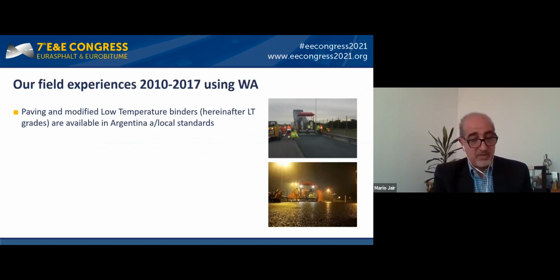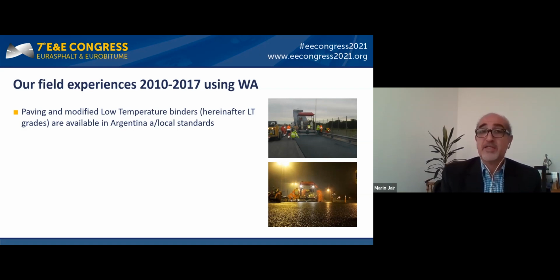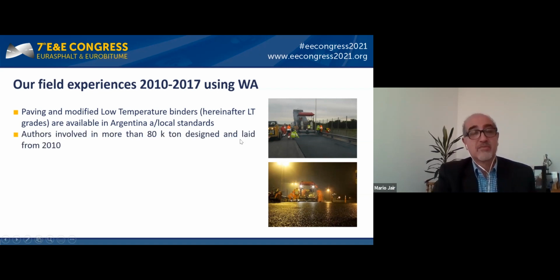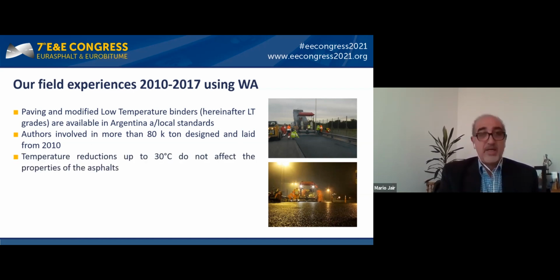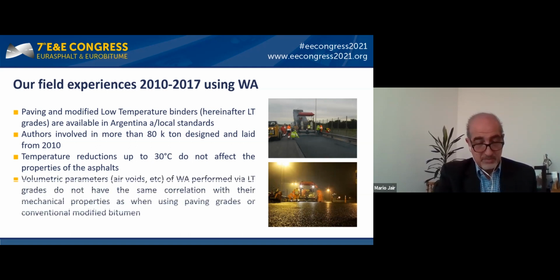Here, a summary about our experiences using warm asphalt mixtures. Paving and modified low temperature binders are available in Argentina according to our local standards. Personally, I was involved in more than 80,000 tons designed and laid from 2010. Temperature reduction up to 30 Celsius doesn't affect the properties of the asphalts. And volumetric parameters such as air voids, etc., of warm asphalt performed via low temperature grades don't have the same correlation with their mechanical properties as when using paving grades or conventional modified bitumen.